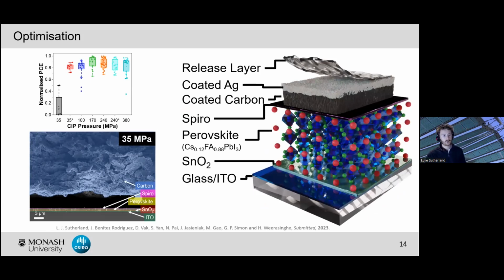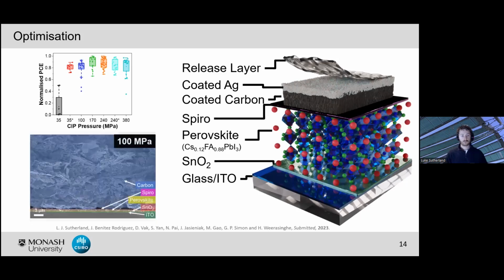Now, this was systematically shown using the CIP by varying the pressure, starting at 35 megapascals, where under the SEM we were able to see large areas of delamination between our carbon electrode and our underlying device. Once we then progress to 100 megapascals, we see much better connection at this interface. But if we look closely, you can still see small cavities at this critical interface between our carbon and spiro, therefore resulting in that lower charge extraction and lower efficiency.